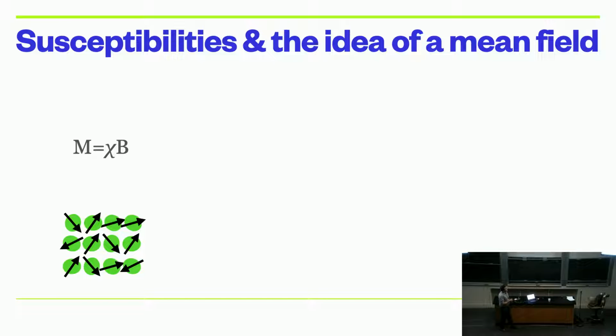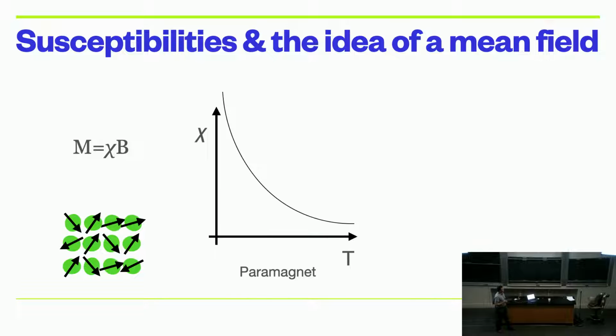Now, the prefactor to this response is known as the susceptibility. The linear response is known as the magnetic susceptibility. At high temperatures, all those spins jiggle around, but at low temperatures, they start to align. So how does this susceptibility, which characterizes the response of our system, evolve as you go to lower and lower temperature? Well, for a system that doesn't order, the susceptibility just grows and grows and grows. What that means is that it's easier and easier to bend those spins in an applied magnetic field as you go lower and lower in temperature. It's basically because those thermal fluctuations become a lot less effective at destroying the alignment of all the spins.